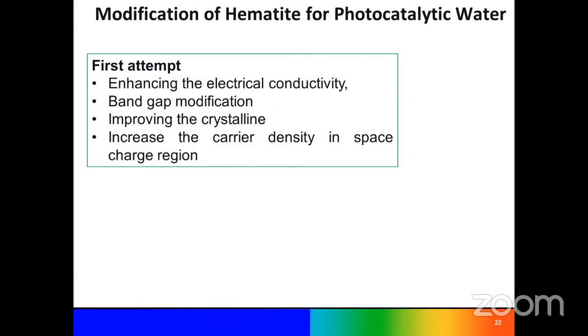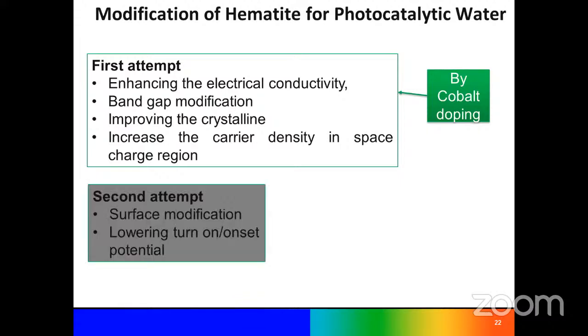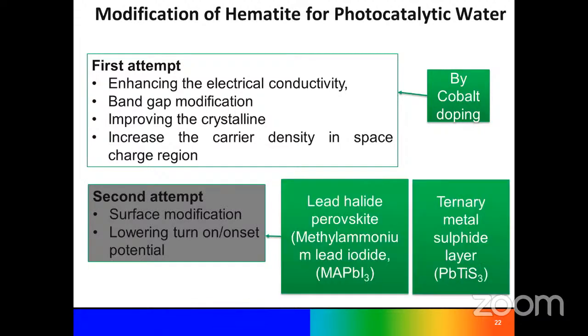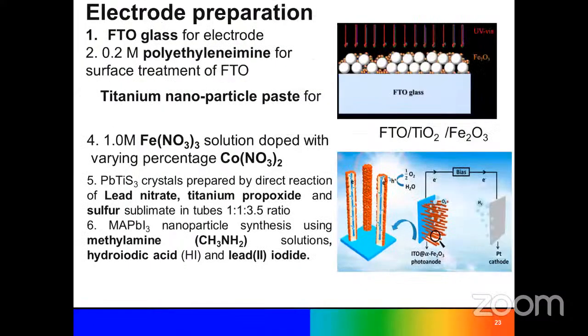So in this case, our first attempt is to enhance the electrical conductivity, then band gap tuning modifications, then improve the crystallinity, then increase the carrier density of the space charge. For these reasons, we tune these morphological structures and the electrical property by doping cobalt inside the hematite material. And for the surface morphology, surface changing, we coat different types of perovskite material on the surface, particularly lead halide material, which is nowadays a very important material for any photoresponse properties.